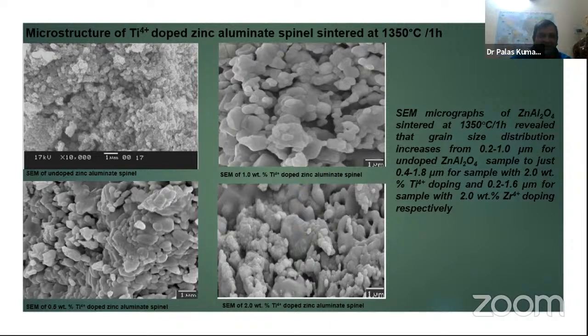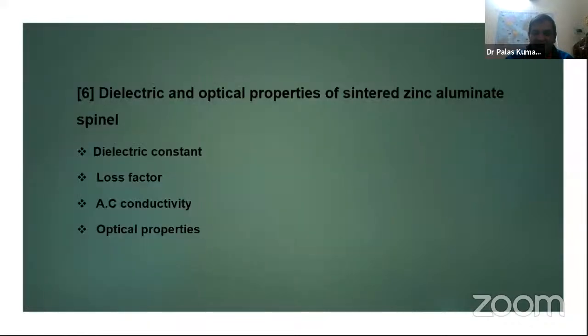So after the microstructure study, this is quite apparent. This is not actually apparent. This is the actual thing which we'll explain later. Both titania and zirconia are acting in the zinc aluminate matrix as a moderate grain growth accelerator, right? So this is the ultimate effect of the addition of the dopant.